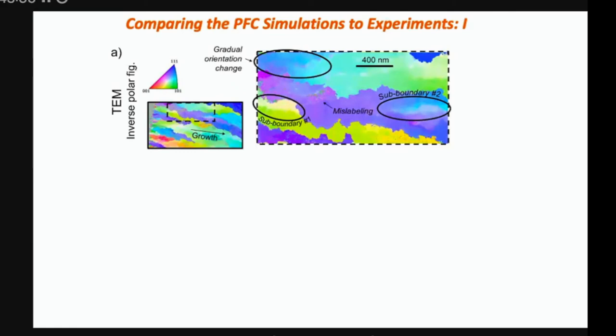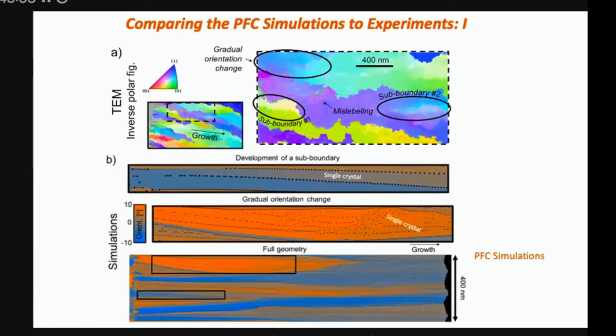And this model is quite cool because it can allow you to simulate crystal growth into an unstable liquid via a void phase or a vapor phase. So the black here is void or vapor, very low density vapor. And the liquid out here is unstable. The thing starts to solidify and it forms this kind of moat or depletion layer of vapor. So the model can do a lot of tricks. And so we applied it to see if it can do this trick here, if it can solidify and capture varying orientations.